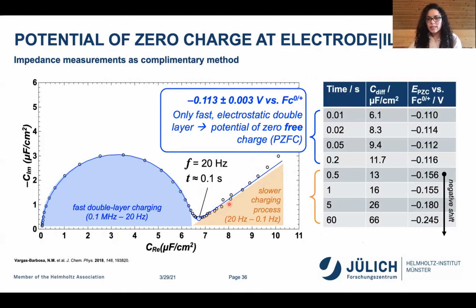And this is actually consistent with our data. So at very short times of our immersion data, we observed a differential capacitance that was pretty similar to what we would get from these kinds of semicircles. And the potential we extracted from the charge potential curves, the potential of zero charge, does not vary significantly. And so we interpret that at these short time scales, when we do this charge potential analysis, we're actually extracting the potential of zero free charge.